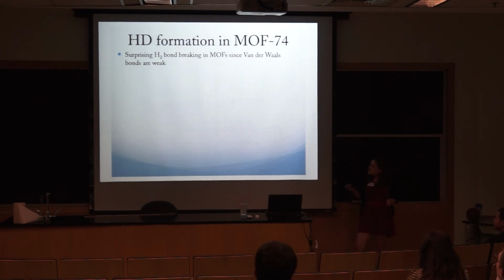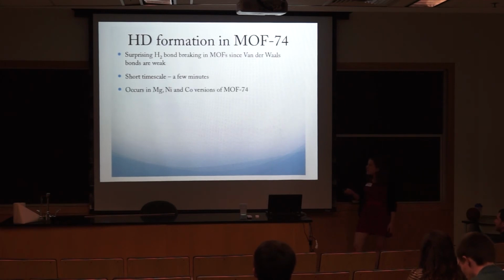So in summary, it's pretty surprising that this catalyzation is happening, and it's exciting because this is the first evidence that the binding is strong enough that dissociation would actually happen in a MOF. It happens in a pretty short time scale, a few minutes, so that's good, it goes quickly. So far we've observed it in the magnesium, the nickel, and cobalt versions of